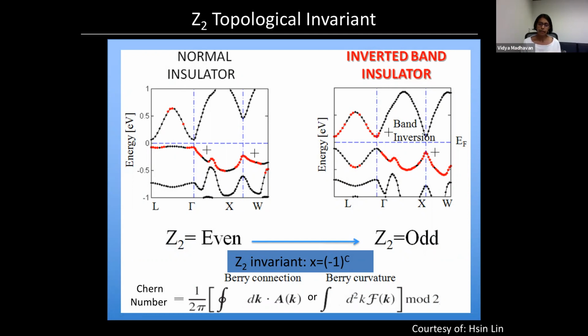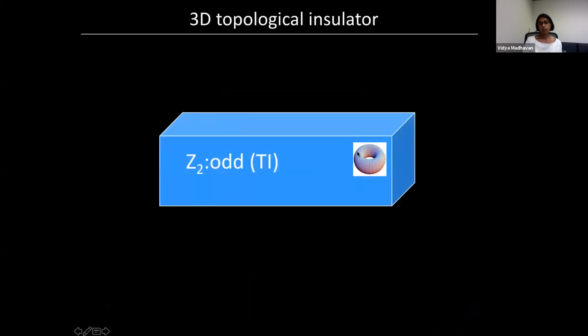Earlier at the beginning of the talk, I showed you the energy momentum dispersion relation for a very simple system where you have just one band. In general, in a solid, these energy momentum dispersion relations can be quite complicated. For example, this might be an energy momentum dispersion for some kind of an insulator. But the interesting thing here is these bands in momentum space form some kind of a topological manifold. And similar to shapes, you can define a topological invariant for these bands. You can show that some bands are topologically distinct from other bands. And as it turns out, these bands that are topologically different are called topological insulators.